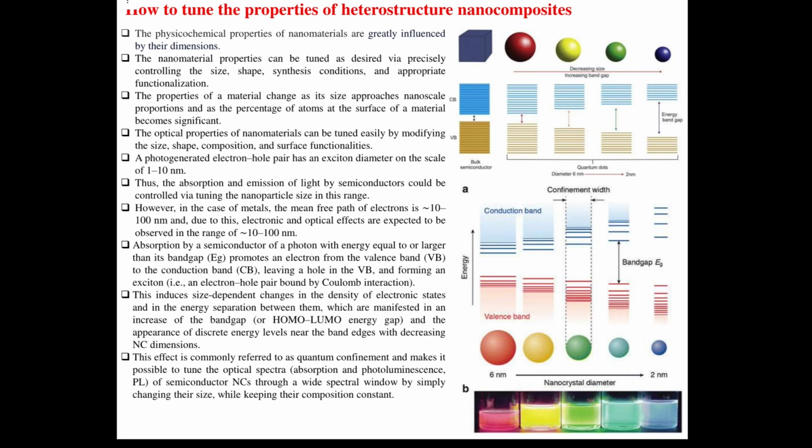For example, we have TiO2, titanium dioxide material here. It's an indirect band gap material with a band gap of 3.2 electron volts. So the absorption edge of this TiO2 lies in the UV region, which limits the catalyst's utilization to the UV region and prevents use of larger wavelength regions of the electromagnetic spectrum. So how can you reduce the band gap of these small structures?